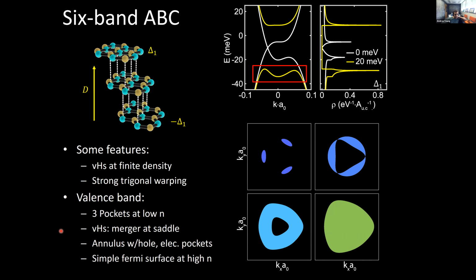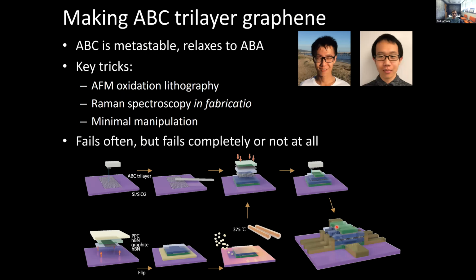Okay, so we can look at this band structure in a bit more detail if you want. And here is a very low density, let's say, of holes. You'll start with 3 pockets. These pockets will then merge at a saddle point where the density of states diverges. As you further increase the doping of holes, you will form an annular Fermi sea, so you'll have a hole-like and an electron-like Fermi surface, and then eventually that electron-like Fermi surface will vanish, and you'll just have a simple hole-like Fermi surface. So that's the basic picture of what you'd expect from a single particle model of ABC.